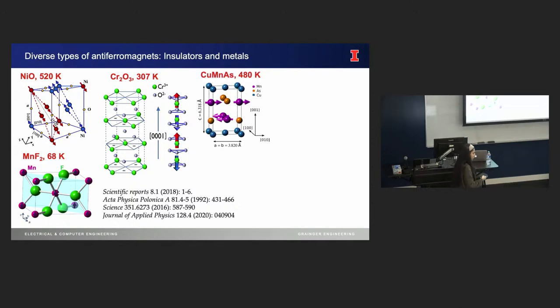I'm not even going to talk about CuMnAs, but I wanted to highlight this material here. This material is a metal. This was the first material in which electrically controlled switching of the antiferromagnetic order was demonstrated. At the time, when I was still a student, it was a Science paper, and everyone was super happy about it. But later on, it was found that the signals that they measured were not related to the switching of the antiferromagnetic order, but rather to Joule heating and atomic motion related to electromigration. Nonetheless, this set the stage for what we could expect in antiferromagnets and generated a lot of excitement in the field about 8 years ago.